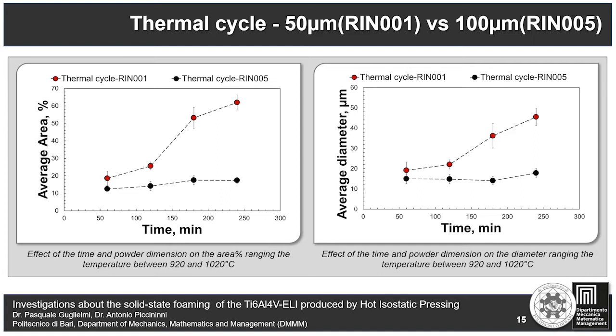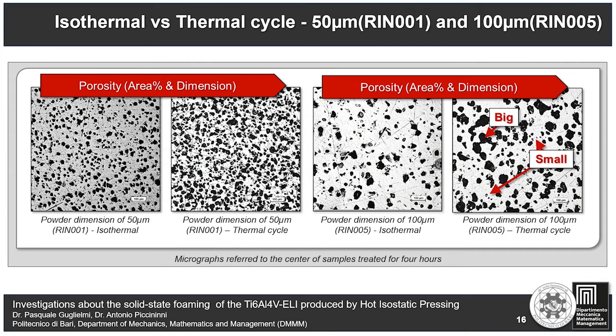On the contrary, the behavior of the two materials differs drastically when we consider the comparison based on a thermal cycle. In fact, in this case, the porosity of the material with a maximum titanium powder size equal to 50 micron is larger than the other one, especially for long times, 3 and 4 hours. This is true for the percentage of porosity, as shown on the left, but also for the average diameter on the right. The comparison of the micrographs obtained for the two different types of material and the two methodologies adopted also confirms the results previously discussed.